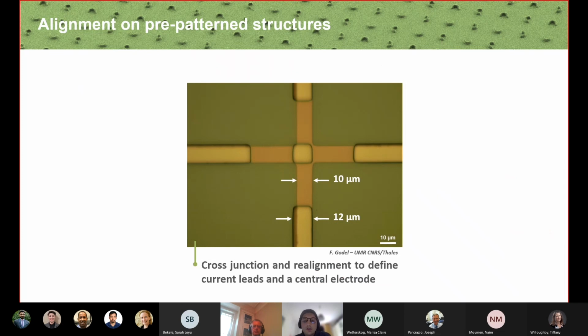That has been fabricated once again with lithography, alignment and etching or lift-off process. Regarding the resolution of the alignment, here you have a typical example of what we can do. Here you have two different layers. The first layer, the orange layer, which has a cross shape, is the first layer fabricated with the system. It has stripes 10 micron wide, and the second layer in yellow, made of four lines with a small island in the middle, has been fabricated followed by an alignment step. You can see that the typical error that we can reach with the machine is about 1 micron. This is for the standard version, the error for the advanced version is lower.